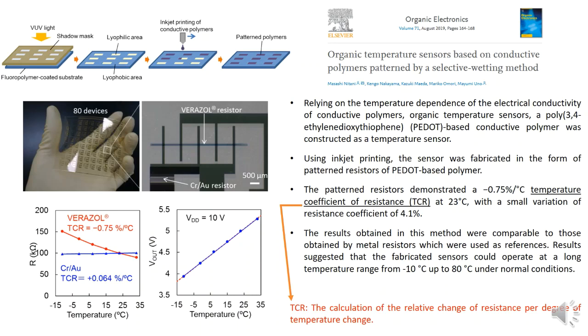In this study, relying on the temperature dependence of the electrical conductivity of conductive polymers, organic temperature sensors based on poly(3,4-ethylenedioxythiophene) as a conductive polymer were constructed. The technology used here is called inkjet printing, and the sensor was fabricated in the form of patterned resistors of PEDOT-based polymer. These resistors demonstrated a temperature coefficient of resistance of minus 0.75% per degree Celsius at 23 degrees Celsius, and the temperature coefficient of resistance, as shown down here, is the calculation of the relative change of resistance per degree of temperature change.